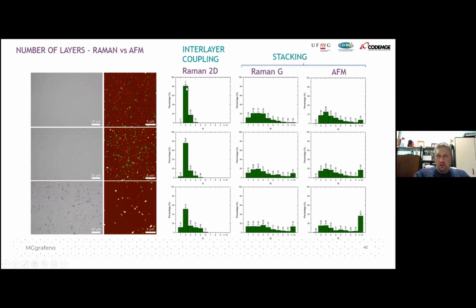Okay, so I would tell you, if I was a company that has a Raman in the lab, I would measure and look at the spectrum and say, okay, this is a 2-layer. Buy my graphene, 2 layers, 3 layers, 4 layers, but this is what the AFM says. It's like 10 layers, 7% in numbers. So this is a lot of mass. This may be like 80% of the mass of graphite. Yeah. So the spectrum would tell, okay, this is bilayer graphene. So the answer is that the Raman 2D band alone is not a reliable way to show the number of layers. Okay, excellent. There are a bunch more questions, so I appreciate your time.